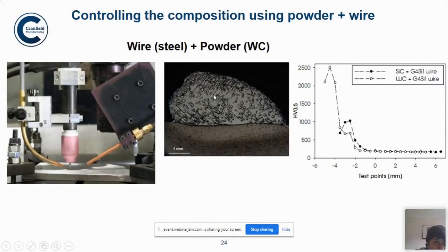So basically this was made for a brake pad application in order to create a brake pad which has very high thermal conductivity, because when the brake pad is engaged against a brake disc, the temperature rises rapidly at the interface, and then what you need is basically the heat to be conducted away so that it doesn't affect the integrity, and at the same time you need sufficient abrasion resistance. So this kind of composite structures are basically created with powder, which is tungsten carbide, and steel wire for such functional applications.